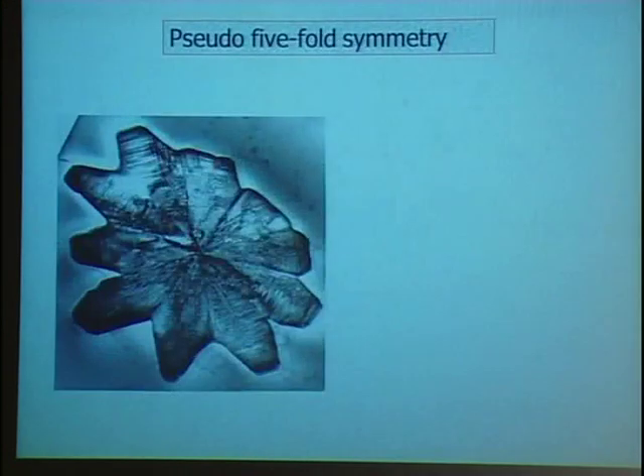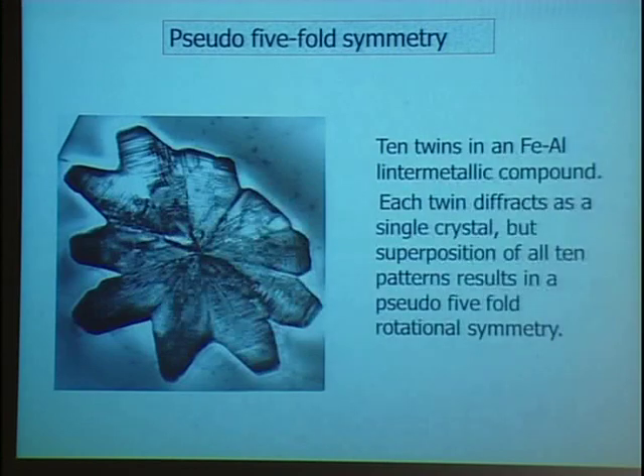But there is a pseudo five-fold rotational symmetry, and this is an interesting picture. This is an image taken also by electron microscopy of a crystal that is found in the aluminum iron system. And I took these pictures in the 70s, many years before the discovery. One of the first pictures I ever took after I completed my PhD. Now, this is a periodic crystal, but there are 10 of them.